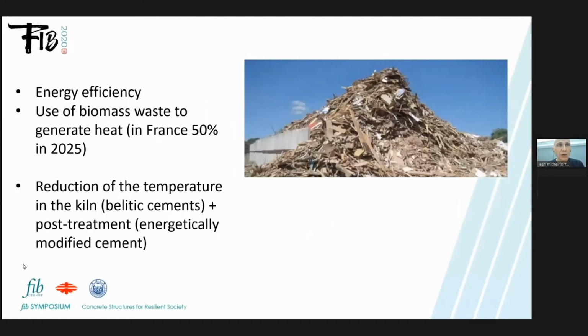Of course, they can work on the energy efficiency of the kiln in the cement factory. In France, they plan to use biomass waste to generate heat in the kiln. The objective is to have 50% of the heat generated by biomass in 5 years. And also, more prospective research is on the reduction of the temperature in the kiln to obtain, for instance, belitic cements. And also we can have a post-treatment, energetically modified cement, to reduce the energy used in the kiln.